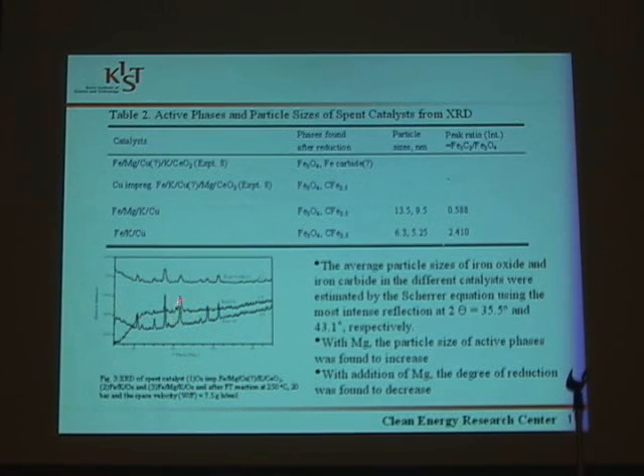So in this XRD, we can observe that the average particle sizes of the iron oxide and the iron carbide in different catalysts were estimated from the most intense peaks at 2 theta 35.5 and 43.1. With magnesium, the particle size of the active phases was found to increase. With addition of magnesium, the degree of reduction was found to decrease. So this table shows.